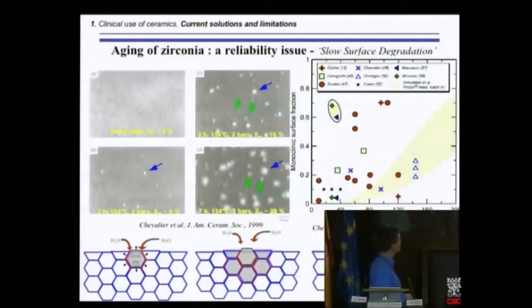But what we expected at that time is that, due to water, there is a transformation of the grains at the surface. So imagine there is one grain at the surface in contact with water. This grain is transforming. Due to the transformation, you have microcracks and tensile stresses on the neighbors. So the neighbors are transforming, and neighbor by neighbor, the transformation occurs.